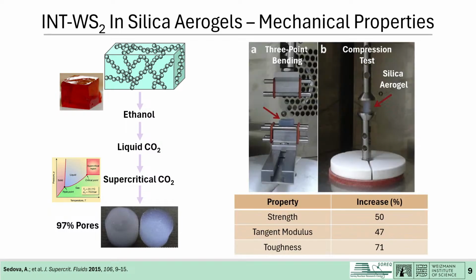So we prepared samples exactly to fit the testing machine. We did 3-point bending. Basically, we have two positions where we place the sample. In between there is nothing, and there is an upper movable part that will press into the sample until it breaks. Compression test, basically, will compress the sample until it cannot anymore. We could achieve quite a high percentage of improvement in strength, tangent modulus, and toughness.